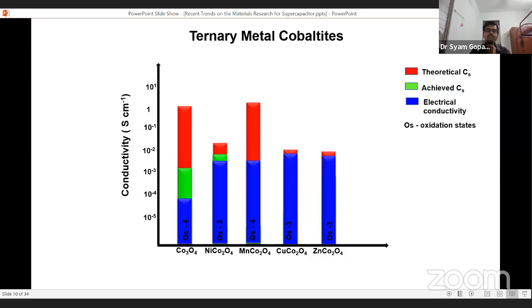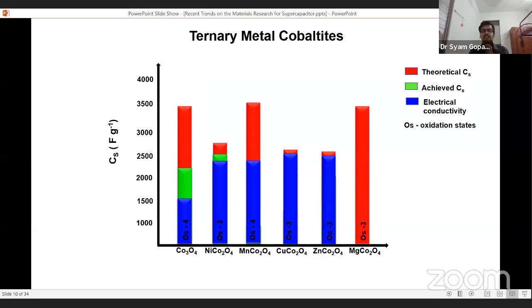And while comparing electrical conductivity, the materials like nickel cobaltate, manganese cobaltate, as well as copper cobaltate definitely have higher electrical conductivity, one or two orders of magnitude higher than cobalt oxide. So another hot material which came into this supercapacitor realm was the ternary metal cobaltates. And recently, it was our research group that explored the utility of magnesium cobaltate, whose theoretical capacitance was also high compared to these, as well as its conductivity.